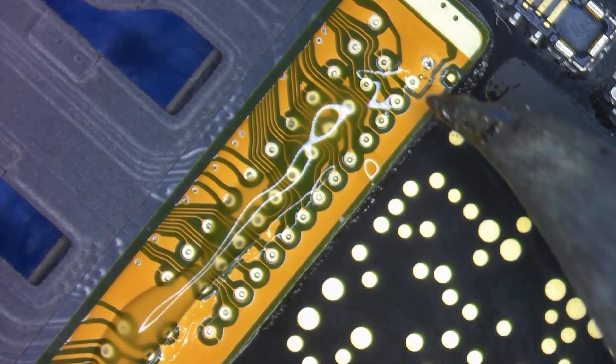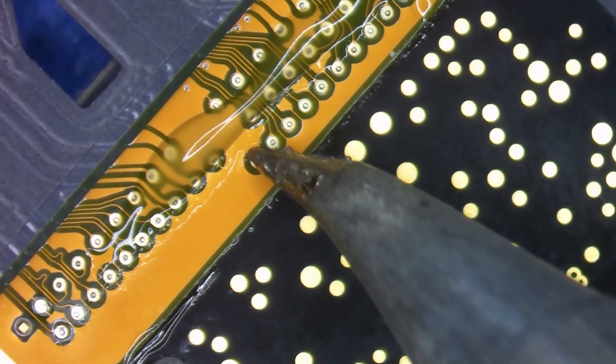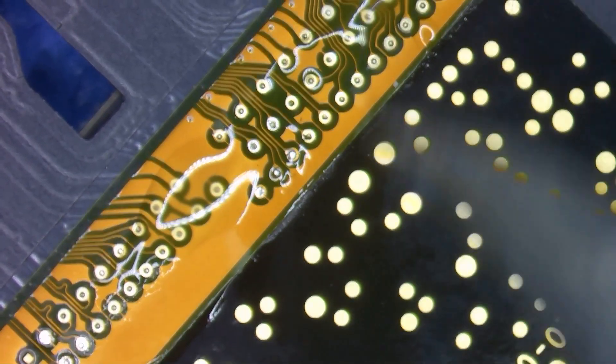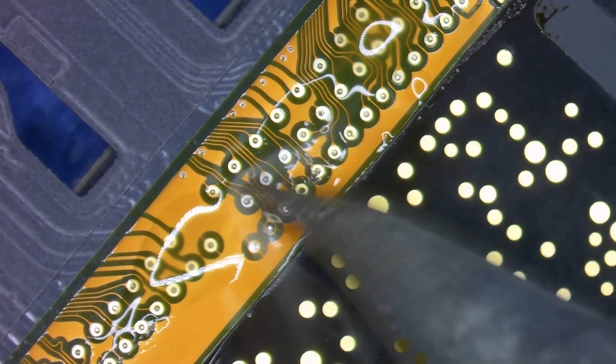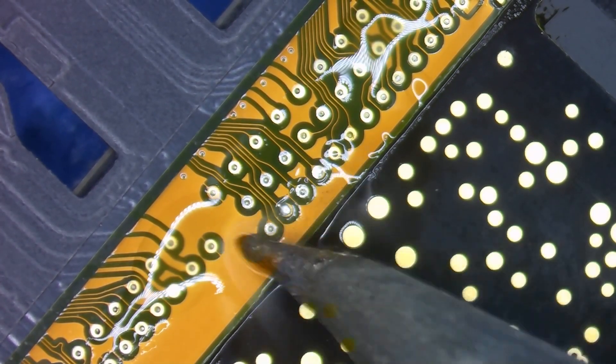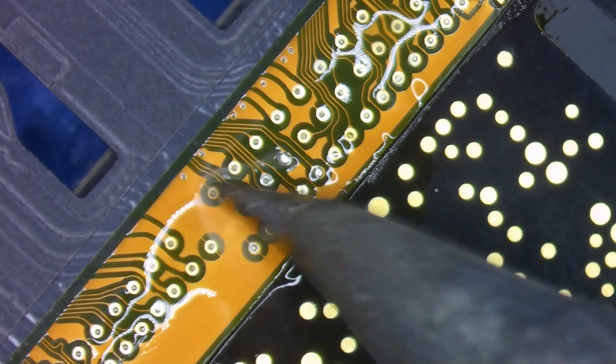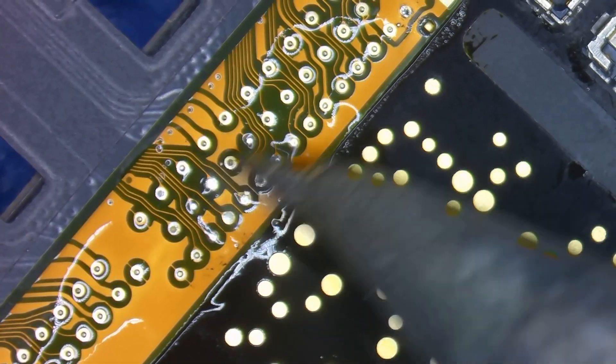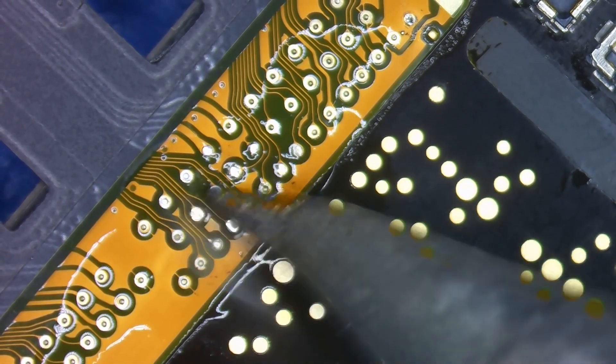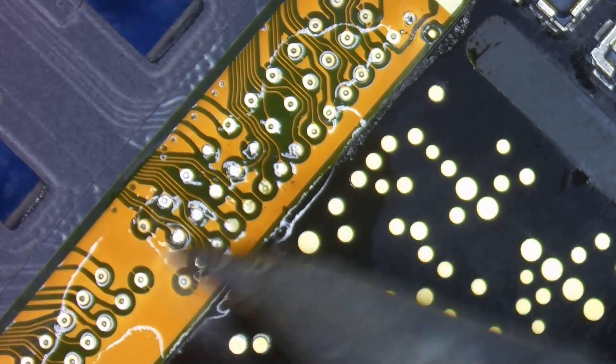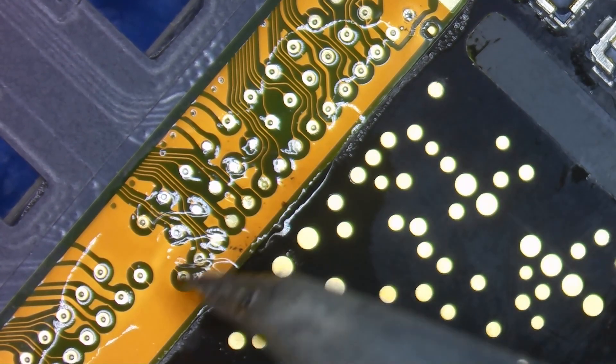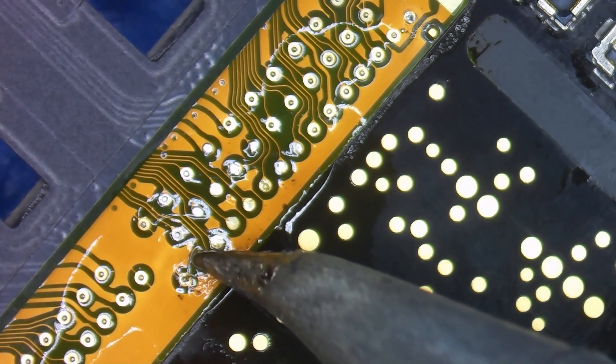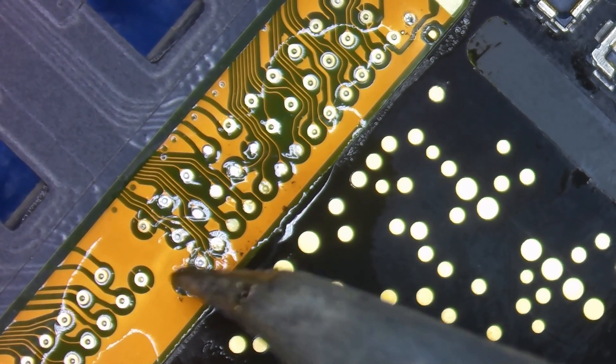Right there, that's good. Now I'm going to go ahead and start to gently pull the solder through each one of those little holes. I'm going to do this by just carefully touching the surface of the flex cable, moving quickly back and forth, slowly letting that flex cable basically lower itself to where it's touching the board itself. And all of the solder has pulled through the holes, connecting each hole through to the board and making a nice solid joint.